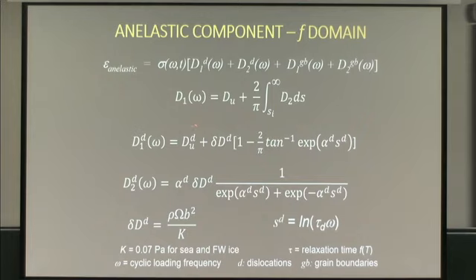If you take that out of phase curve and integrate it, you wind up with what's called the storage compliance. And the out of phase part is called the loss compliance. Both of these are frequency dependent in the frequency domain here. All these geometric terms do is determine how that relaxation is distributed, either in frequency or in time after start of loading. I won't get into the dislocation mechanics, but we can relate our position term to the dislocation density, and that in turn drives this loss compliance. So these are the quantities that we're interested in getting at. The model relates those to the actual dislocation density.